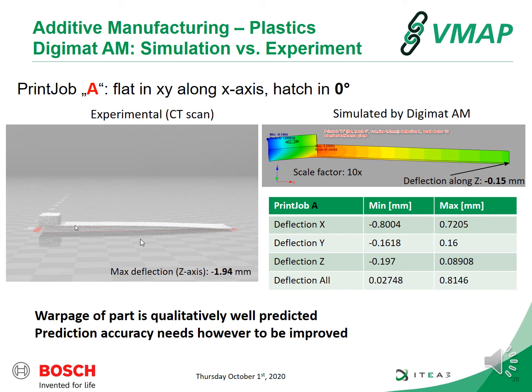A comparison between the simulated warpage and the experimental one was done by analyzing with CT scans the warped parts out of the printing process. As you can see in these two pictures, the qualitative deflection of the part is well in accordance. However, the accuracy of the warpage prediction still has to be improved.